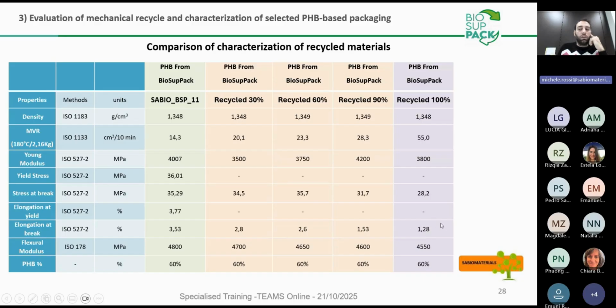Most important, as you can see here, for 100%, we are around 1.28, so quite no elongation. But it's maintaining similar the flexural modulus around the same number. We saw a decrease of the value, probably due to the fact that higher recycled content inside the formulation means a lower molecular weight inside the formulation, so we lost some properties for the flexural modulus.